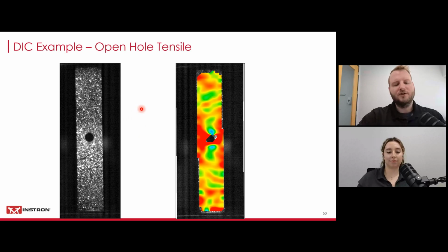So just a couple interesting ones that we thought we'd show you. So we have an open hole tensile test here. So you have the open hole specimen, and you can see that random speckle pattern that you need to apply to your specimen. One technique to do this, there's many different ways, all kinds of ways people do this. What I can recommend is just taking a toothbrush with some white paint. You put the white paint on a toothbrush, and then you just flick the toothbrush to get the paint flying onto your specimen. It needs to be random, which is a fun challenge.